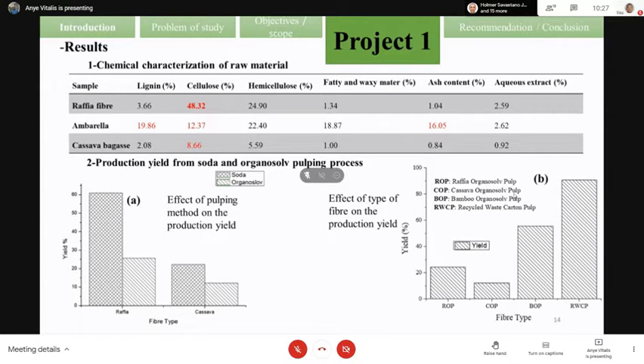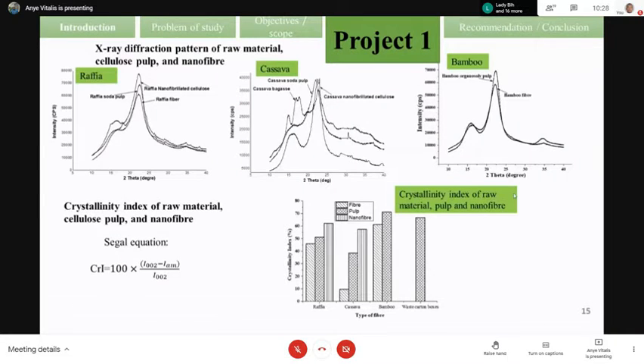Now we study the effect of the type of pulping on the type of fiber, using raffia, cassava, bamboo, and recycled fiber. We realize that with bamboo and recycled fiber, we have a high production yield, which shows a significant improvement of the pulping, so we can have a good economic impact by using those types of material. We also study the X-ray diffraction from the raw material to cellulose pulp to the nanofibrillated cellulose.